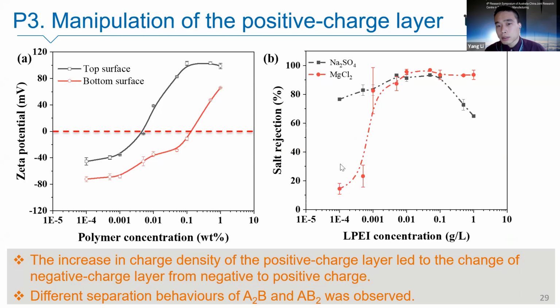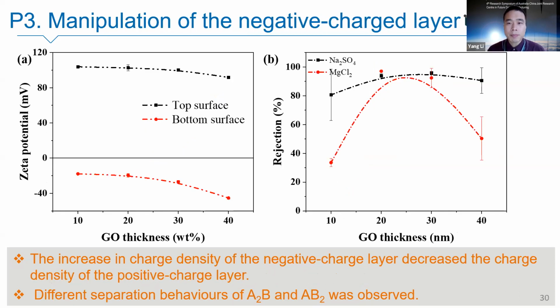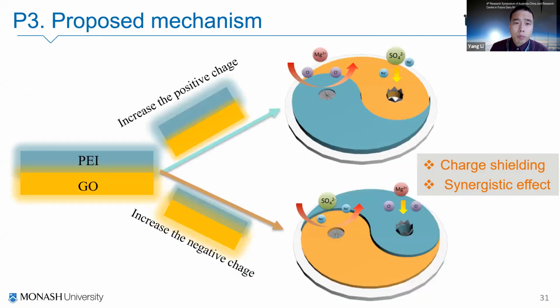The salt separation generally gradually increased for the magnesium chloride. When the polymer concentration reached 0.1 gram per liter, we found both salt ions can be removed at a higher rejection rate. So we found that we can use this Janus structure for manipulation of the membrane performance. Similarly, we have done another experiment to increase the negative charge properties by increasing the GO thickness. We found similar phenomena as the previous one with a different separation mechanism. The proposed mechanism is shown here.